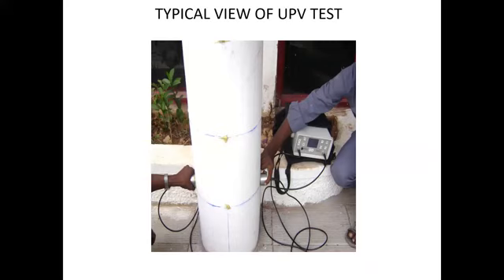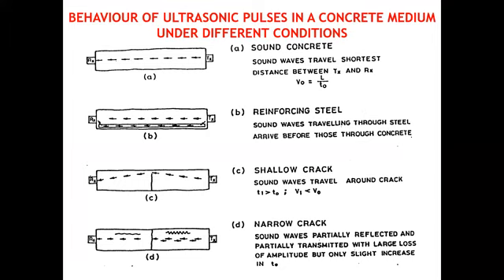This is the indirect method, where both the probes are kept on the same surface. When you go for an indirect method, the code allows you to add about 0.5 kilometer per second to 1 kilometer per second as an additional value. If the concrete is sound, waves travel straight forward, and we get the velocity. If you've got heavily congested rebar in the concrete, sound waves travel through the rebar and you get a much higher velocity, and you need to be very cautious about whether to take these values as concrete velocity or not.